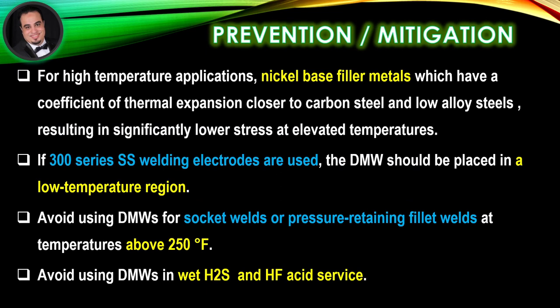Prevention and mitigation. For high-temperature applications, use nickel-based filler metals, which have a coefficient of thermal expansion closer to carbon steel and low-alloy steels, resulting in significantly lower stress at elevated temperatures. If 300-series welding electrodes are used, the dissimilar metal weld should be placed in a low-temperature region. Avoid using dissimilar metal welds for socket welds or pressure-retaining fillet welds at temperatures above 250 degrees Fahrenheit. Avoid using dissimilar metal welds in wet hydrogen sulfide and hydrofluoric acid service.